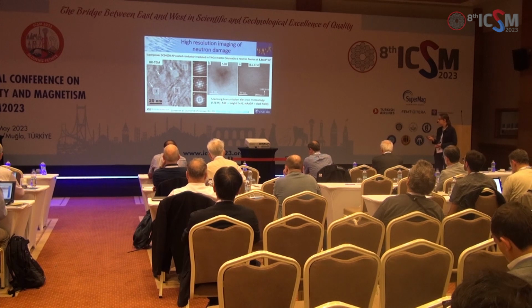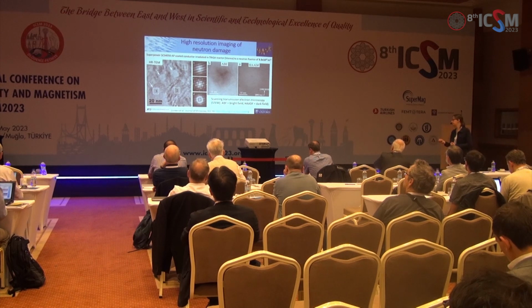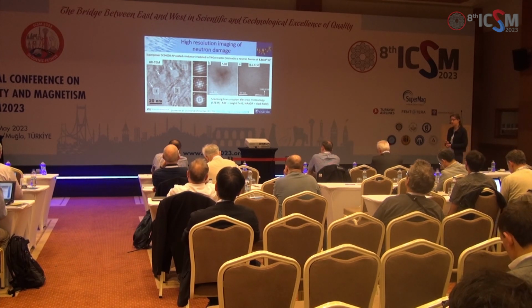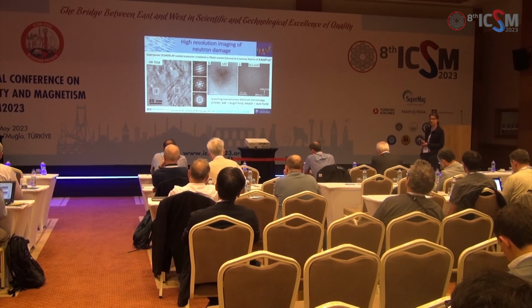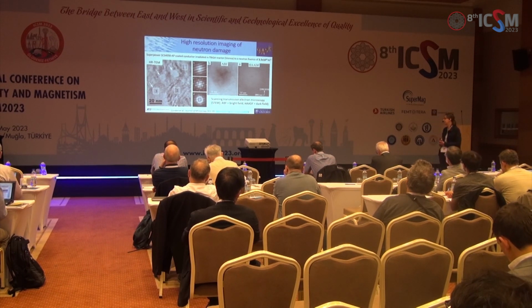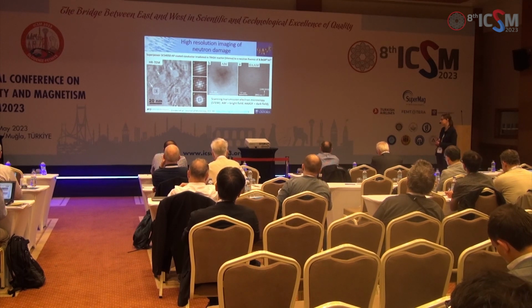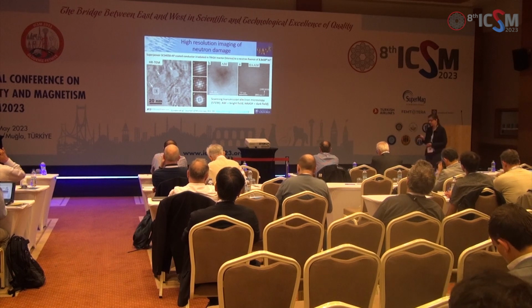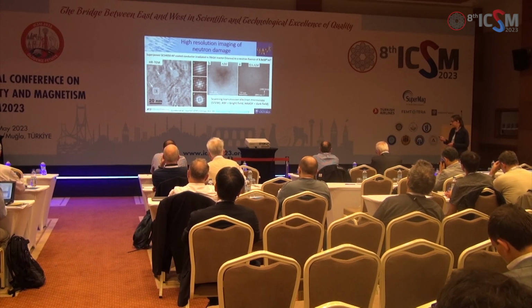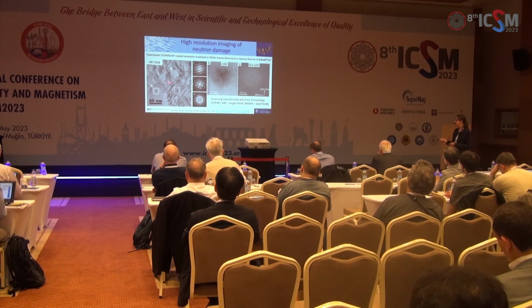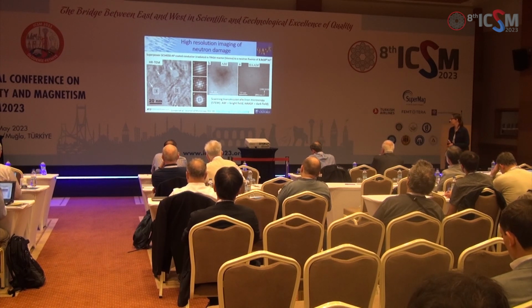The interesting thing, though, is that this doesn't really explain what's going on with the decrease in critical temperature. These big features here can explain what happens with the critical current density, because these things are excellent flux pinning sites. So as we put more of these in, our critical current density goes up because we get stronger flux pinning, until they get too close together, and then critical current density comes down. But TC is a property of the matrix. It's a property of the majority of the material, which is where the current goes through. So something must be happening in these regions that still look relatively perfect. And that's one of the questions that I've been looking at. What kind of damage is going on in those regions that we can't see in the TEM?